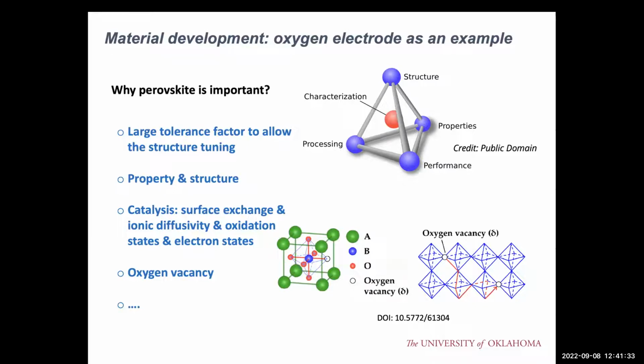So for the oxygen electrode, most oxygen electrodes are based on perovskite materials. When you hear perovskite, you may hear a lot about solar cells, right? And the perovskite is also commonly used for the oxygen electrode. So perovskite is a structure consisting of octahedra of BO6. B is the metal at the B site, which is an octahedral structure, as you see here in the lattice.